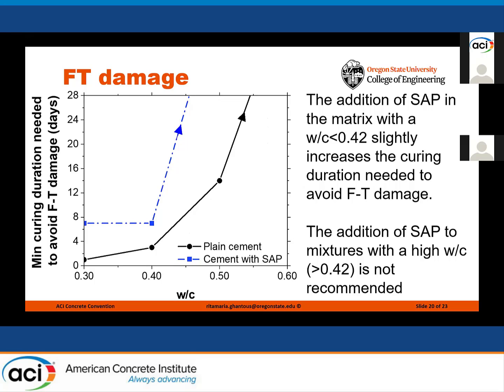So if we summarize the data we've been looking at in this slide, we have the minimum curing duration needed to reach a residual strain below or equal to 0, absence of freeze-thaw damage, on the y-axis, versus the water to cement ratio on the x-axis. In black, we can see the values for plain cement, and in blue the values for samples with SAP. It can be concluded that the addition of SAP in the matrix with a water to cement ratio below 0.42 slightly increases the curing duration needed to avoid freeze-thaw damage. And the addition of SAP to mixtures with high water to cement ratio is not recommended.